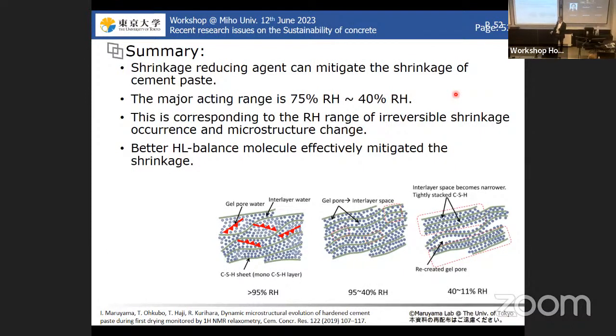And it seems that this gel pore space is reduced under drying, and that happens during the first desorption. But if we add SRA with a hydrophilic and hydrophobic balance, and with short molecules, in this case SRA can exist in the gel space, and it mitigates some reduction of the space between the sheets, and then the shrinkage reducing performance was attained. So this kind of SRA is very effective for the shrinkage of the hardened cement paste.